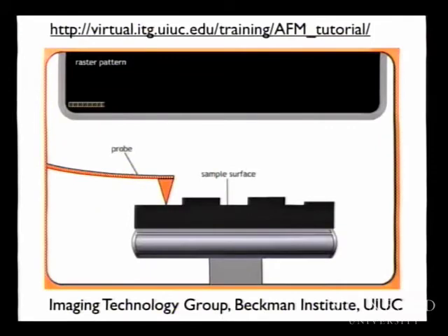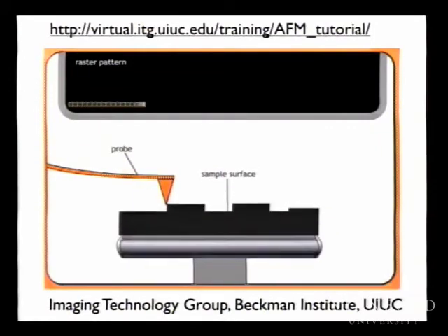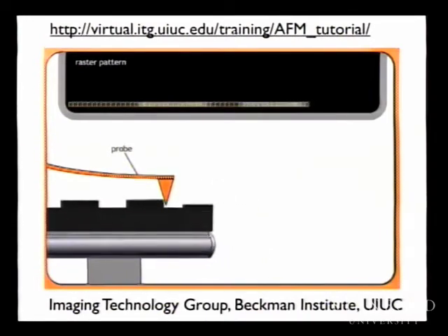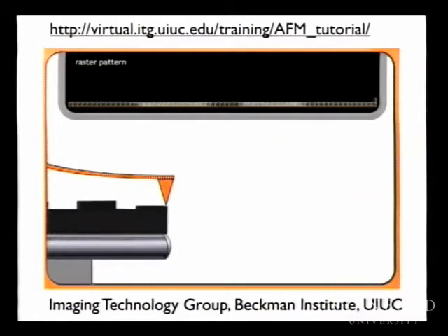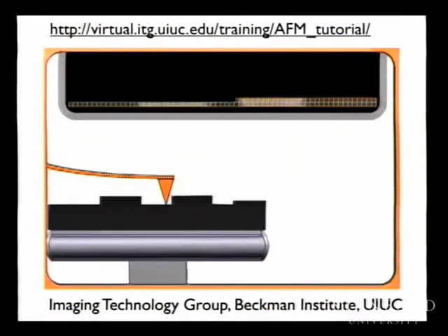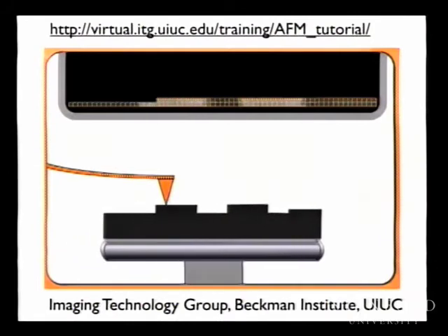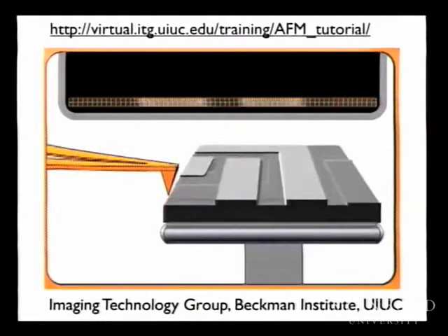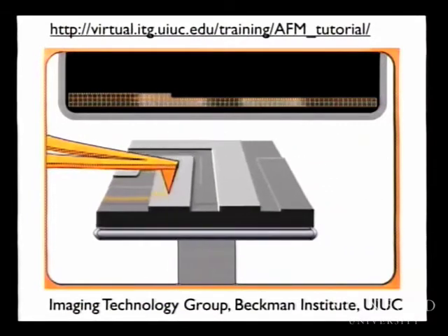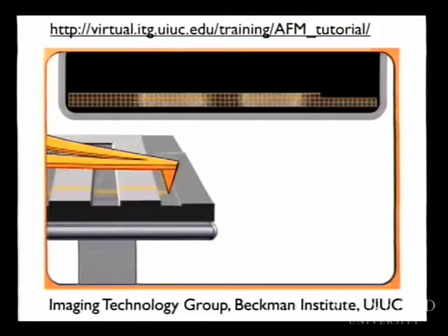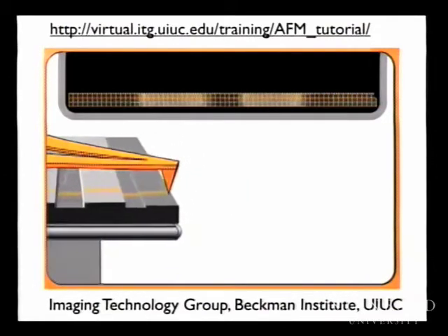All right. So the way we visualize these things is using atomic force microscope. We can't easily visualize them in solution, so we have to plunk them down on a surface and then use this relatively destructive technique to image them. This is a fine micromachined needle, and it's raster scanned back and forth across a surface. There's a laser beam that's bounced off this needle. You measure the perturbations of the needle as it drags back and forth across the DNA. So that's how we're going to measure these two-dimensional DNA shapes.